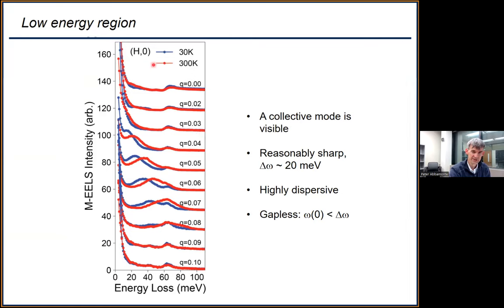So these are two different temperatures. Blue is 30 Kelvin, red is 300 Kelvin. And you can see one thing that's kind of clear. There's a phonon here at about 60 milli-eV. That phonon's dipole allowed. You can see it in infrared optics. Let me not speculate. I think it's a B1U mode, if I recall. Anyway, it's a known phonon. And so that's nice that we should be able to see that, and we do.